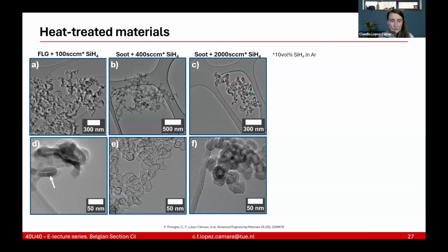So the top pictures are zoomed out, the bottom pictures are zoomed in. If you see picture D, picture E and F, it's actually the same thing. We departed from soot, exactly the same soot, but we changed the mass rate, the quantity, of silane. Obviously that translates to the quantity of silica, sorry, that we get at the end. And therefore we can create thinner or thicker shells, or thinner or thicker walls, on the hollow nanoparticles. We also checked further whether they had porosity at all, and they were actually mesoporous.